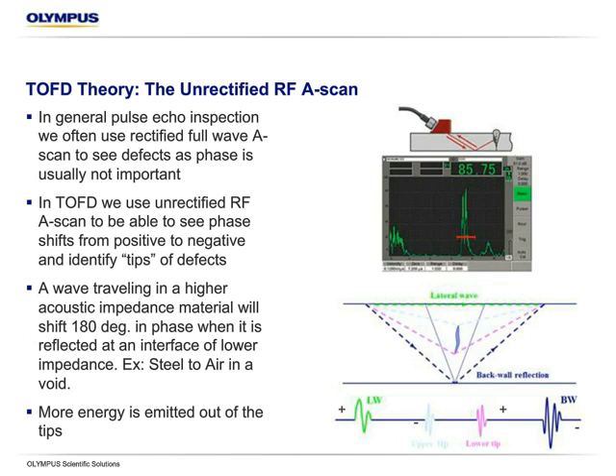So a little bit about the wave modes. Typically with most flaw detection, as well as many thickness measurements, a lot of times we use what's called a full wave or a half wave, positive or negative. There's just different ways of displaying the energy that we're receiving back. So if we took a normal weld inspection with a pulse echo shear wave probe, for example, we're taking a sum of all the energy and basically just showing the positive component typically. So we're taking all the positive and negative components of that energy and displaying them in one positive way.